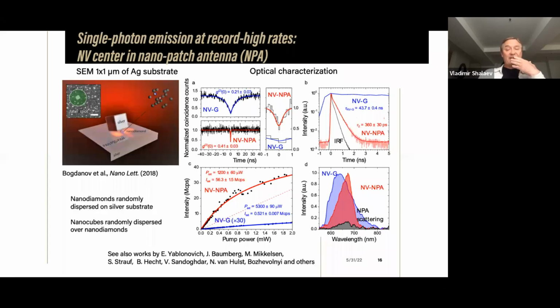So what we obtained with this experiment is that the rate with which single photons were emitted, when they found themselves in this nanopatch antenna, increased by roughly 100 times, reaching 30 million single photons per second, which is at room temperature, it's important to say. But if you take into account the transmittance of your system, which was 25%, collection efficiency 50%, and efficiency of your photodetector 70%, the actual rate with which the single photons were emitted at room temperature was already close to half a billion single photons per second, which is quite impressive. And importantly, the number of photons increased by a factor of 100, and the lifetime decreased by a factor of 100, meaning that all this enhancement goes to a radiative channel, because it could also be non-radiative, but it's clearly radiative, which is important.